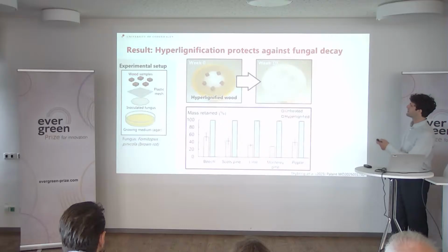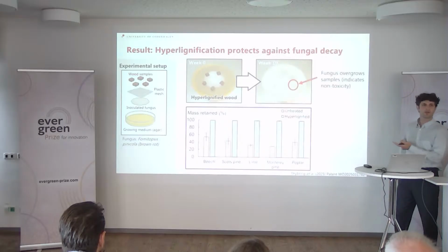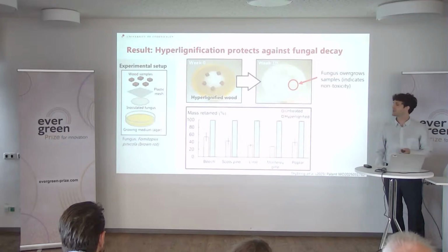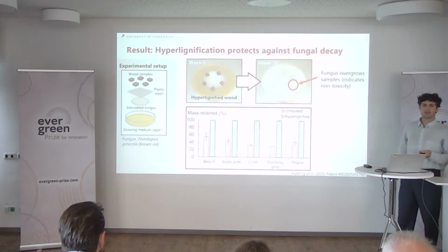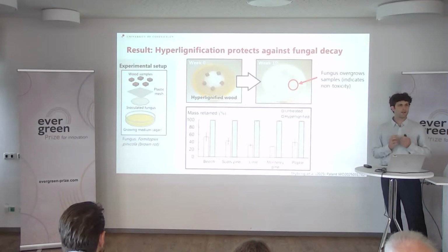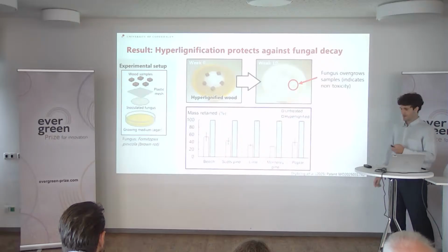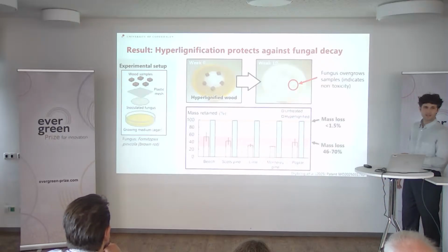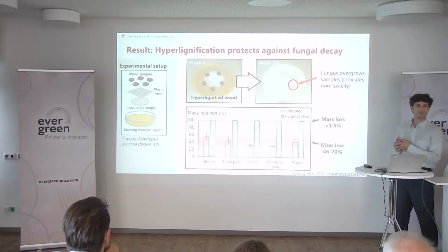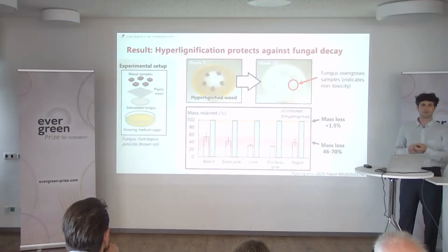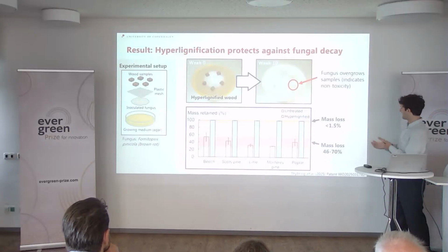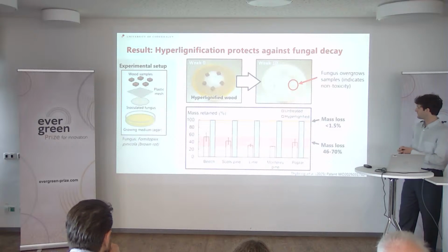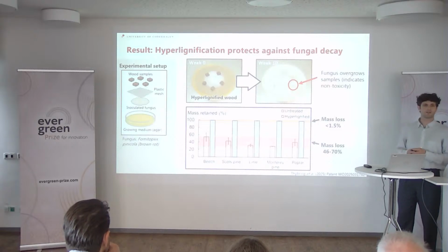What we see here is hyperlignified wood after 10 weeks, and actually the fungi could overgrow the samples, which is an indication that it is non-toxic. The hyphae could grow around the wood. But when we looked into the mass loss in hyperlignified wood across all the species that we tried, the wood was barely touched, while for the untreated samples, there were huge mass losses after 10 weeks.